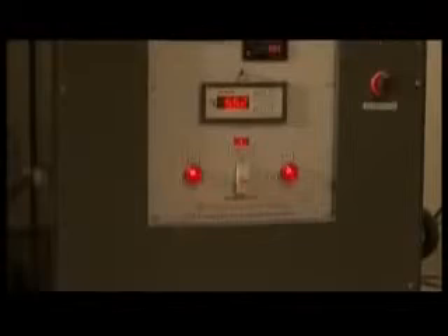A fully charged extinguisher is exposed to a salt spray for 24 hours. Following a drying period of 24 hours, the extinguisher is then washed carefully to remove salt deposits. At the end of the test, the body of the extinguisher must remain intact without any signs of corrosion.